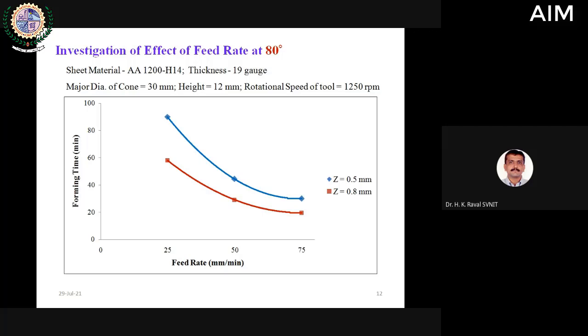Because this is not die punch forming, where the production rate is high. It is single point incremental forming. It takes a lot of time to form one component. You can see here the time taken for forming one component ranges from 20 minutes to 60 minutes for a depth of forming of 0.8, and for a depth of forming of 0.5, it takes around 35 minutes to 90 minutes. 90 minutes is 1.5 hours, so it is a very lengthy, time consuming process. It adds to the cost of manufacturing. So time saving is also one of the key aspects for economical production. Hence, a result analysis was done on how forming time can be controlled, and we found that a higher depth of forming and higher feed rate will definitely help the forming of the component.